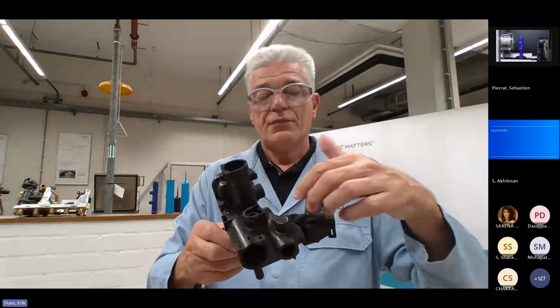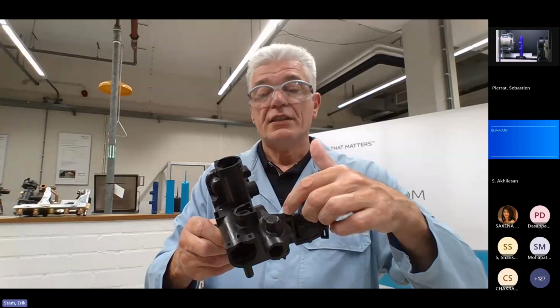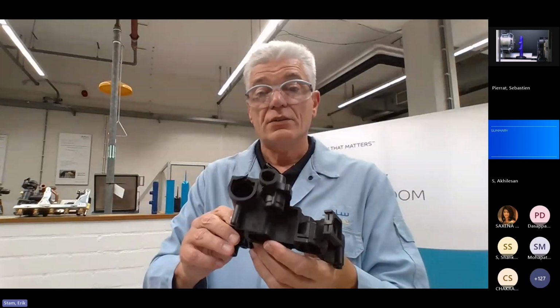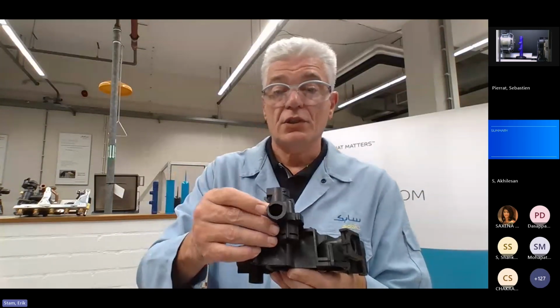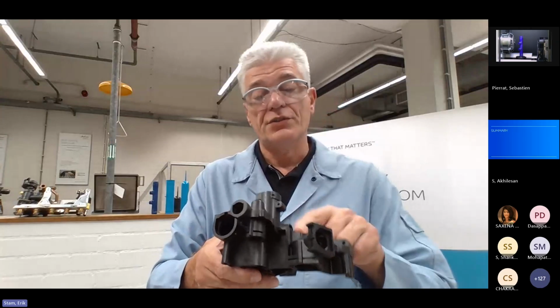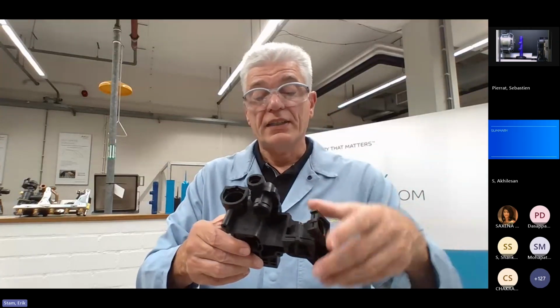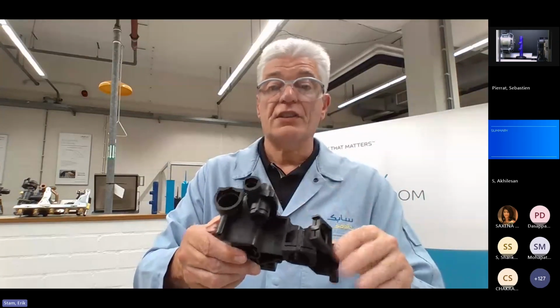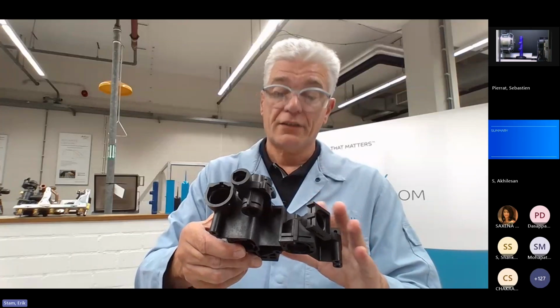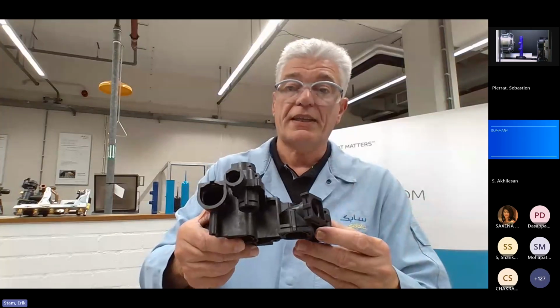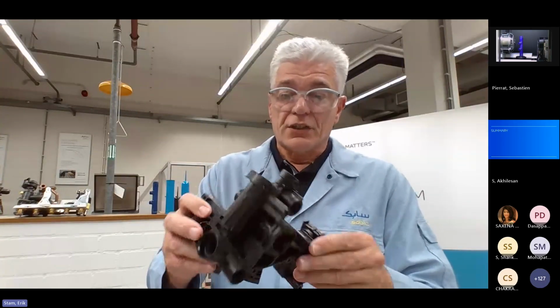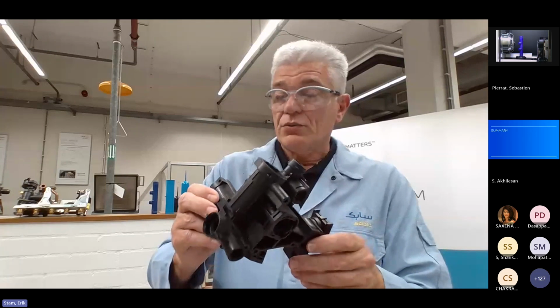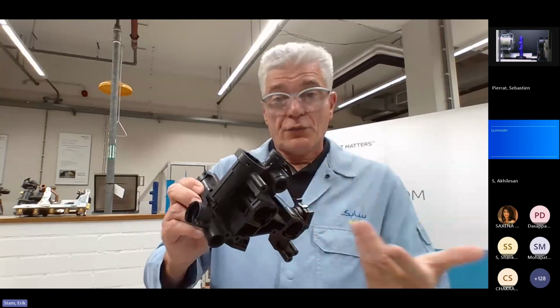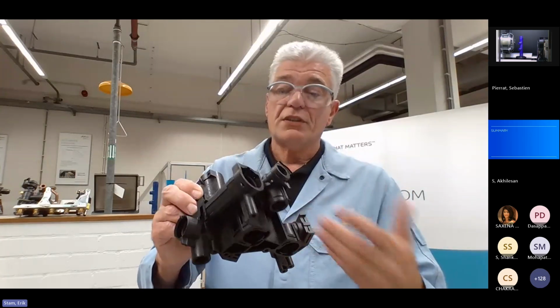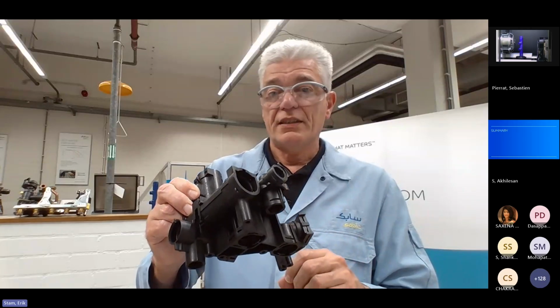This part is injected from one side, which means that the fibers are orientated in all different directions. And because it's in hollow shape, so you have the channels, it means also that you will have various weld lines on different locations, and this all together determines the end performance or the performance of the application in total. So that we need to validate here. But of course, we have also internal samples which mimic a part of what we see in the real application. So let's have a look at that.